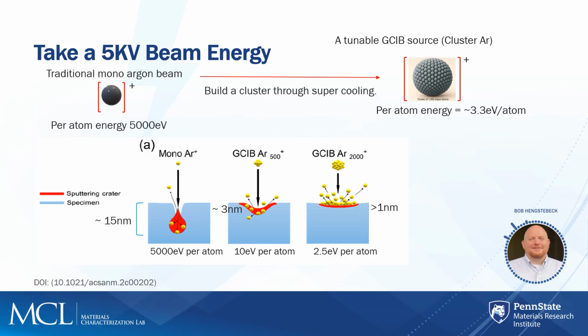For one thing, the large clusters, because of the size of them, actually come in at a much lower velocity. On top of that, the clusters themselves being supercooled, they break up very easily and allow a lot of that energy to be spread instead of going directly into the material, towards the tangentials or away from the surface. And so we can essentially get it to the point where any subsurface damage that occurs is within the information depth, or some very minor portion of the information depth that we're going to analyze. And as I said, we'll show that and how it looks in a couple of slides going forward.